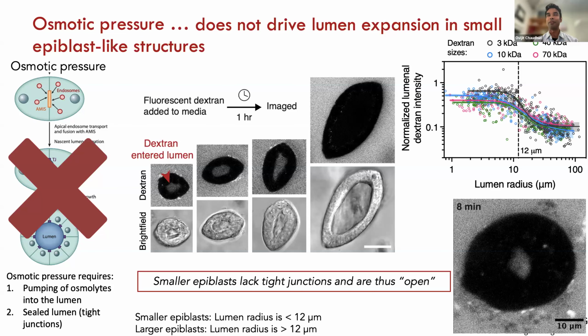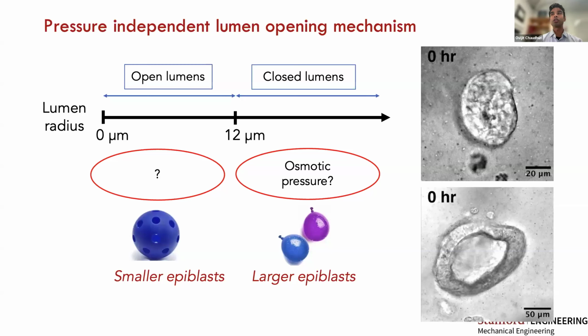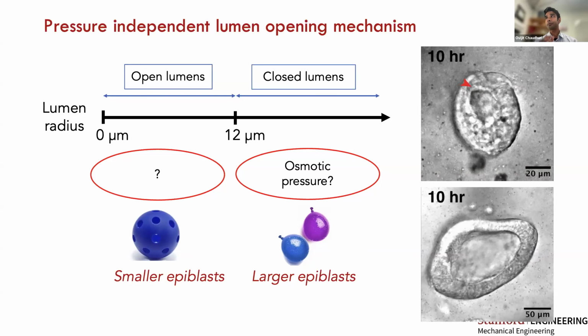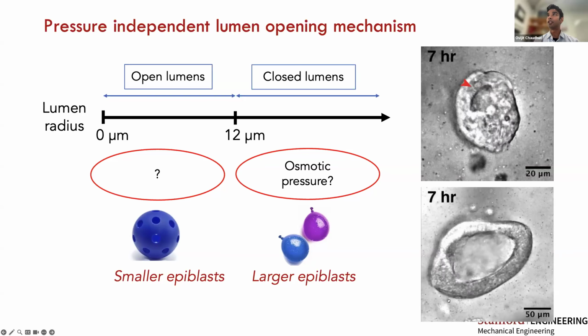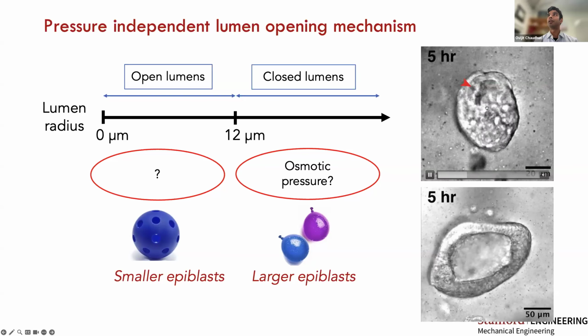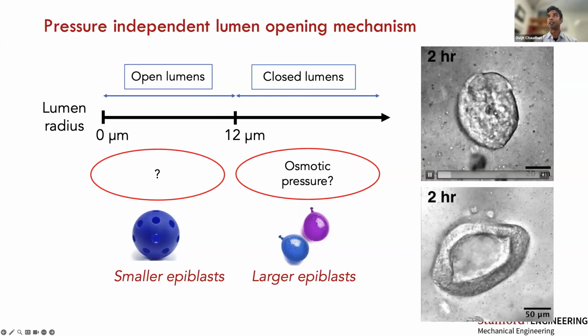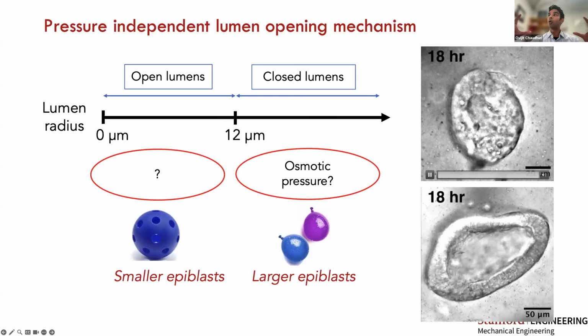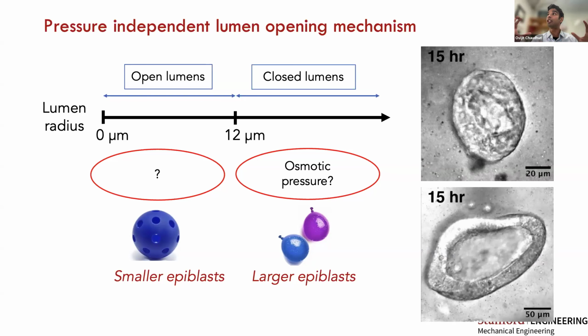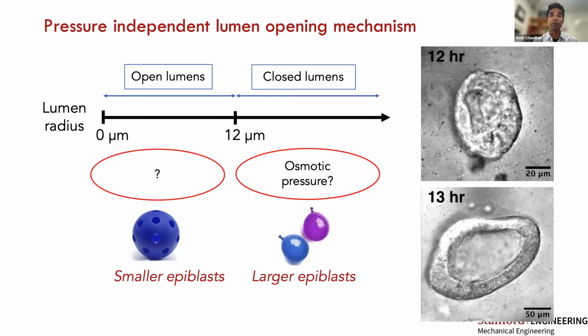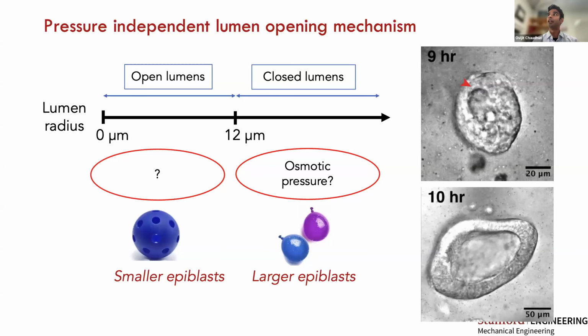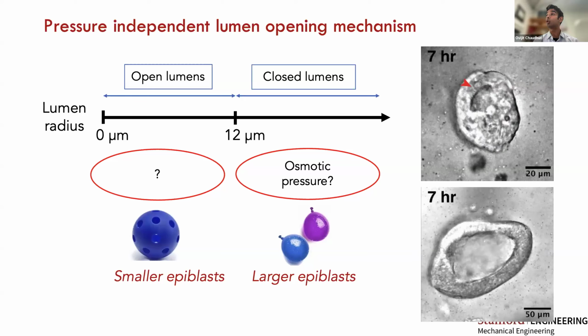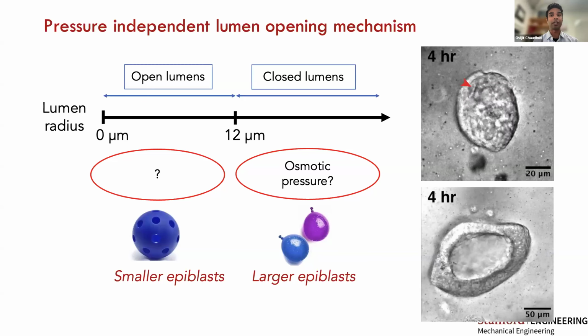And this is not the only piece of evidence; we have some other evidence to support this idea as well. So if it's not osmotic pressure gradients, what could drive this early lumen expansion in these epiblast-like structures? One clue was that associated with this lumen expansion, as we see here in these clusters, the overall cluster is expanding as well, so it's pushing out on the hydrogel. And these are fairly stiff hydrogels, on the order of 20 kilopascals.